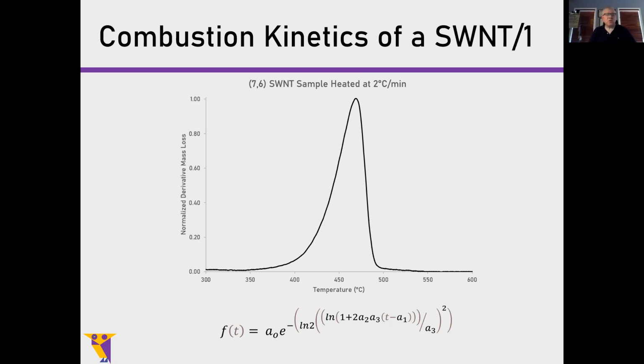This is a tube called a 7-6 tube. The 7-6 tube is a non-conductive, or rather a semi-conducting tube. And this is sold by Sigma Aldrich as a very pure nanotube. And this is the derivative of the mass loss curve done at 2 degrees a minute in a TGA in an air atmosphere. And what you see on the bottom there is a kinetics curve. That is something called the Fraser-Suzuki equation for the type of kinetics that occur at these temperatures for the combustion of materials.